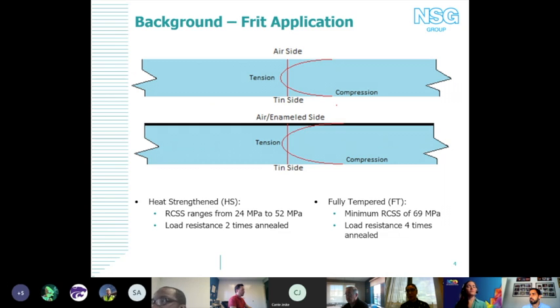So what this does is, and this is something that whether it's fritted or not, when it goes through the tempering oven, you essentially are creating this residual compressive surface stress in the glass, and that's what determines whether it's heat strengthened or fully tempered. In this top picture, you'll see this is a piece of glass that doesn't have any frit or enamel on it, and you have this symmetric residual stress within the glass, where you have tension in the center and you have this layer of compression along the surface, and that's really what's giving it the additional strength that you're looking for.